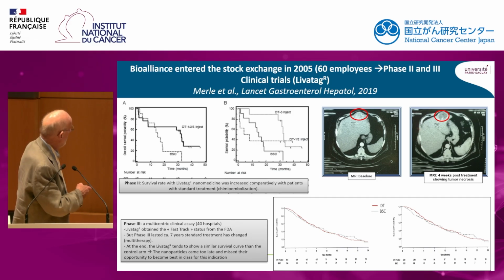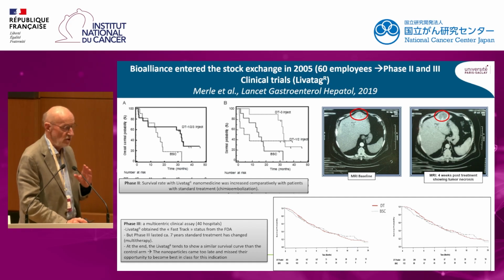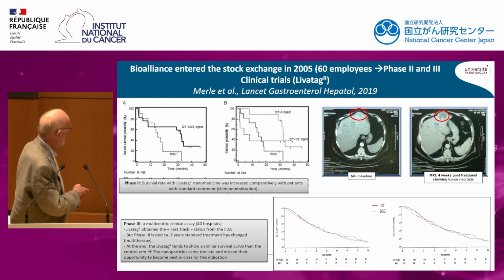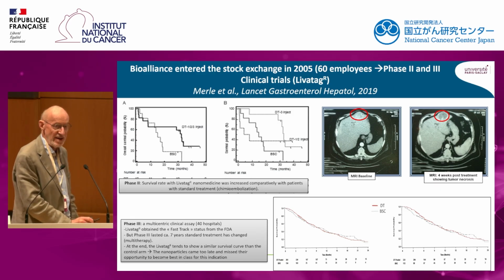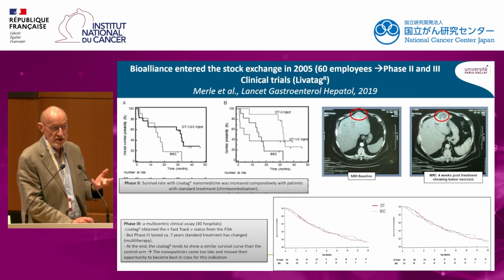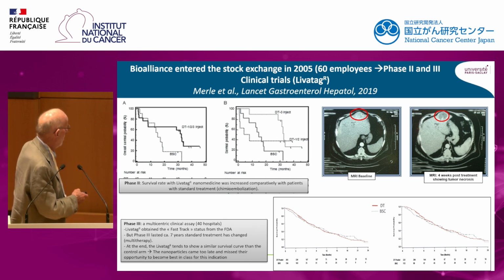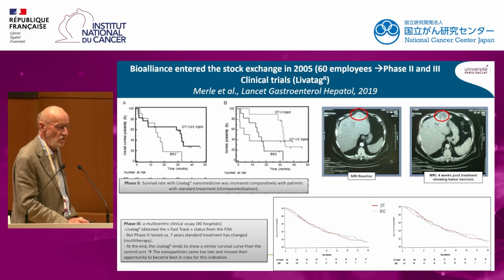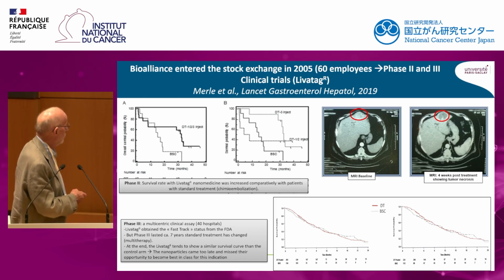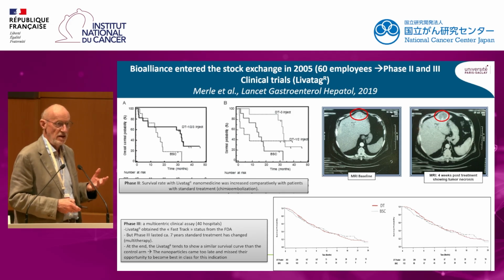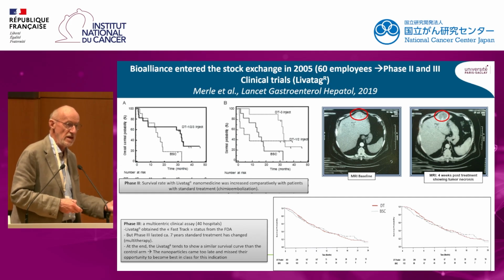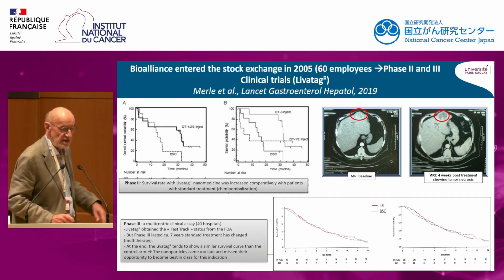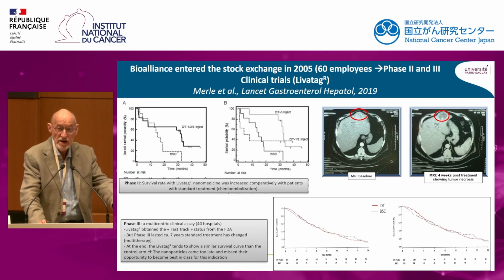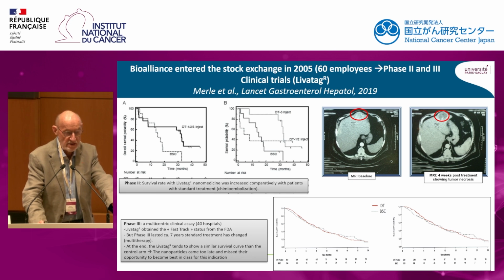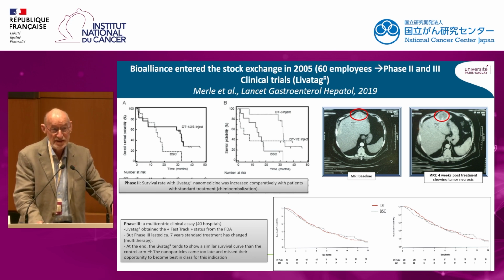And this allowed us to start with a phase 3 clinical trial, which was a multicentric clinical assay in over 40 hospitals. And very rapidly, the Livatag obtained the fast-track status from the FDA because the nanomedicine was well tolerated by the patients. But at the end, as you can see here in the survival curve, the Livatag tended to show a similar survival curve than the control arms. Because in the meantime, the standard treatment has changed from the chemoembolization to a multitherapy. And unfortunately, the nanomedicine came too late and missed the opportunity to become the best in the class for this indication, and no nanomedicine could be put on the market.